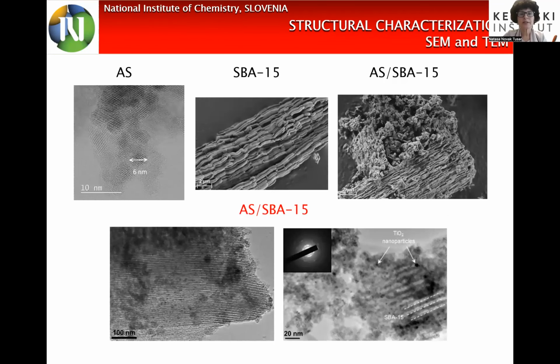So these are structural characterizations with electron microscopy. So we see colloidal titania. We defined titania also with electron diffraction and X-ray diffraction. So we determined the structure of anatase, and we can see here SBA-15 and the colloidal SBA-15 composite. Here we also see the combination with the transmission electron microscopy investigations, and we can see this partial destruction of SBA-15 and some titanium nanoparticles in this structure.